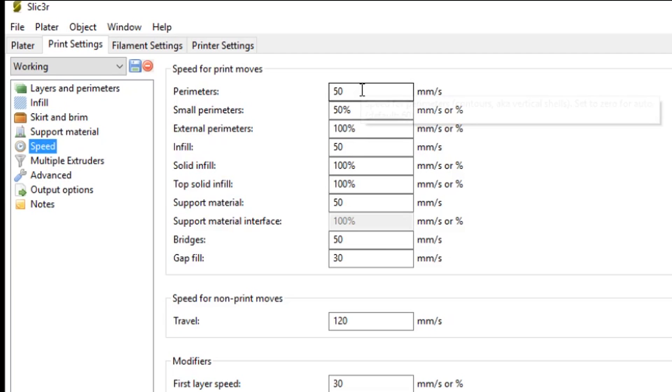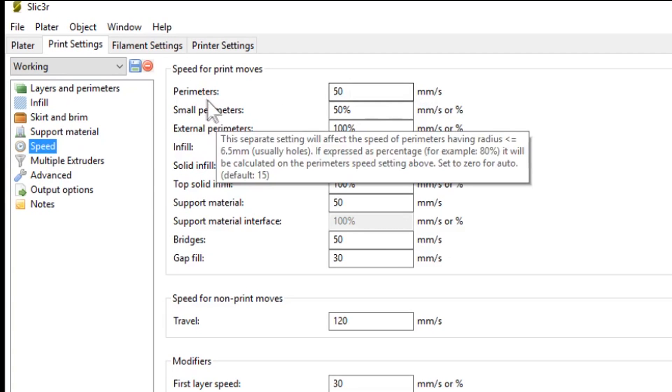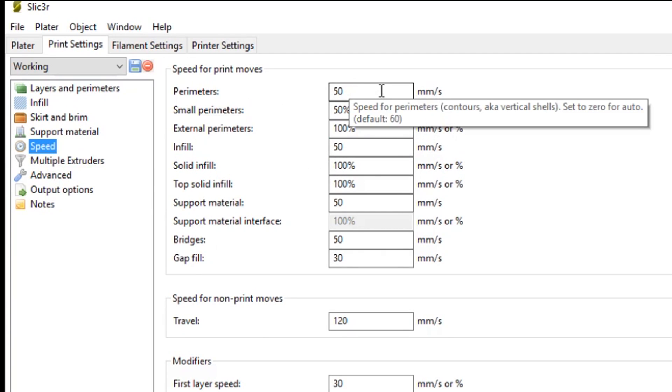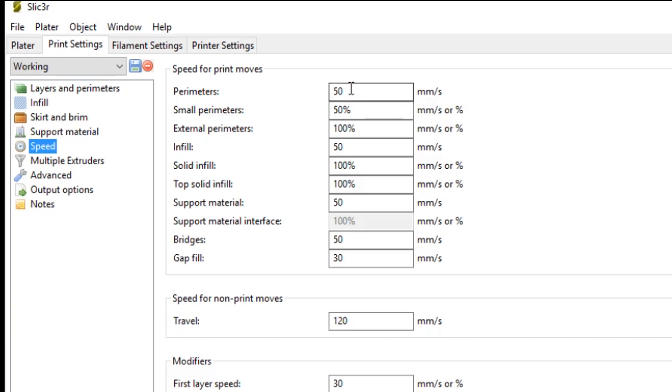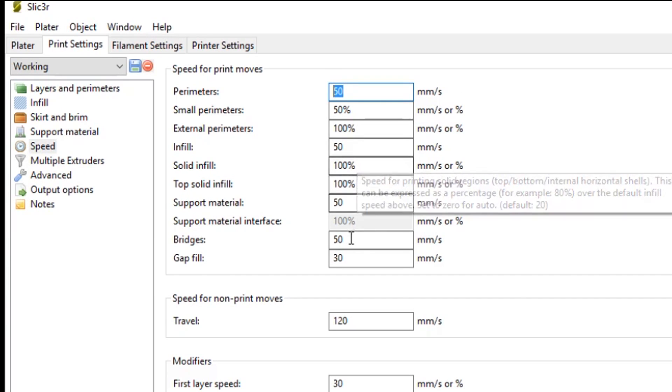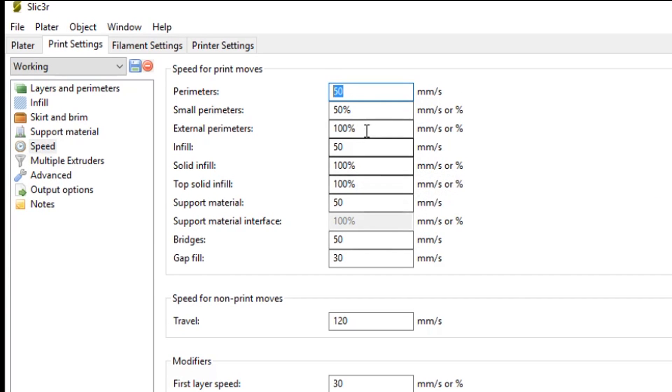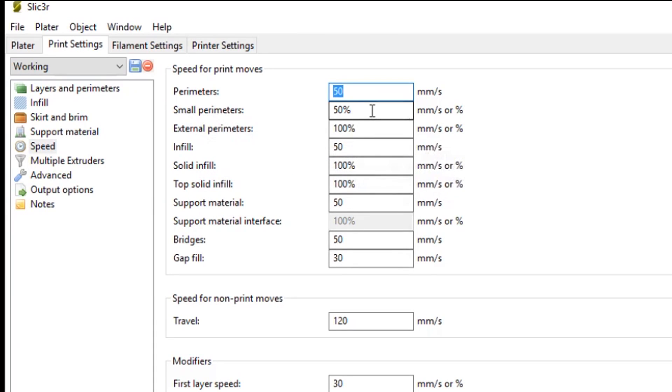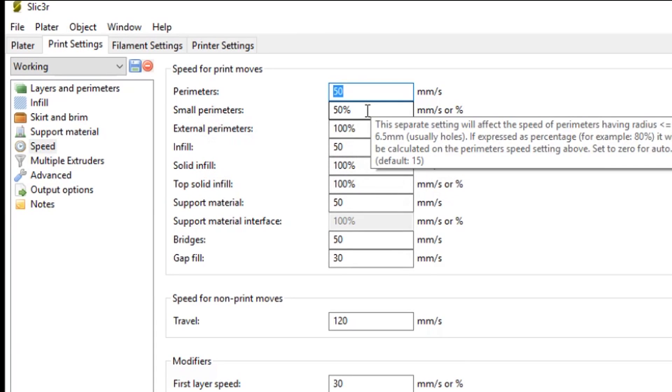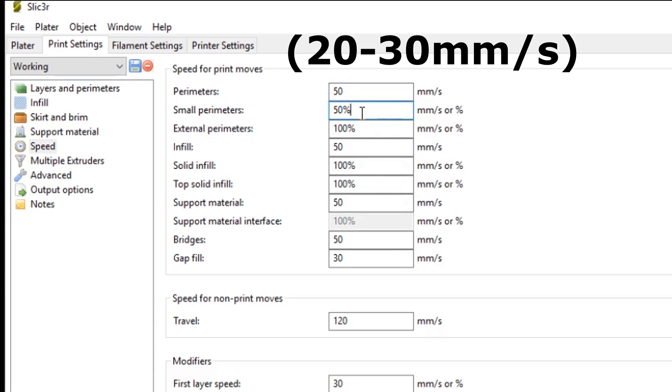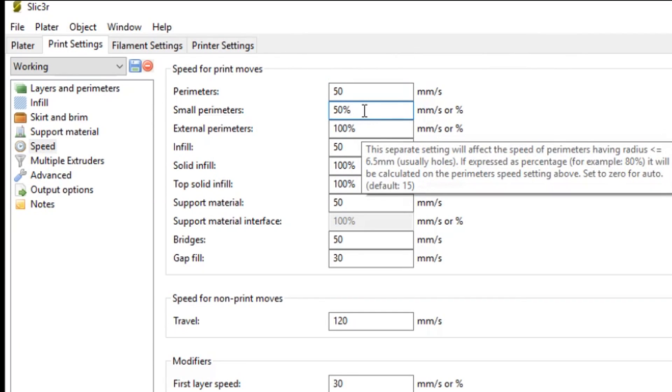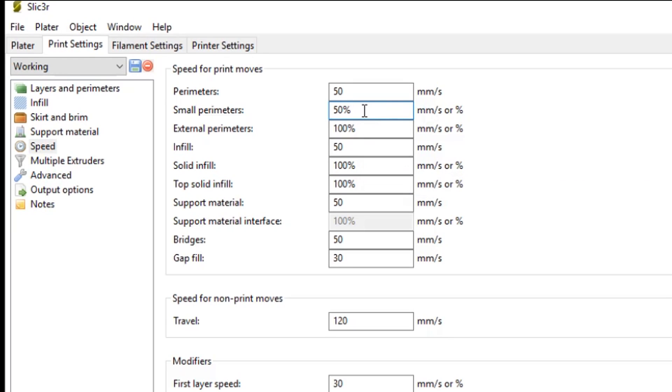Next up we have speed. This is the actual speed of the prints itself. And as I'm printing in PETG, I'm kind of limited to print speed here. So I'm printing at 50mm a second. Every other print type here, I'm printing at 50mm a second as well, except for small perimeters. For small perimeters, I recommend reducing that to anywhere between 20 and 30 millimeters. As a really small perimeter needs to be printed more slowly so the detail comes out and isn't lost in the speed of the print.